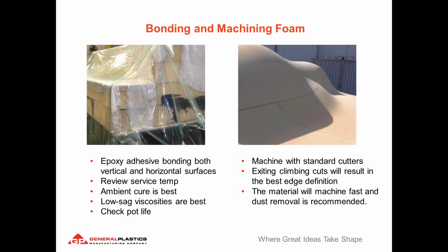We also recommend to vacuum bag the final bond up before the glue has gelled, and that will allow you to consolidate and remove any air bubbles out of the glue and prevent really large bond lines. And after machining, you can see the bond lines in here. This is a very easily machinable foam, and you want some type of dust removal, air hoses, vents, vacuums to remove the dust as it's being machined.